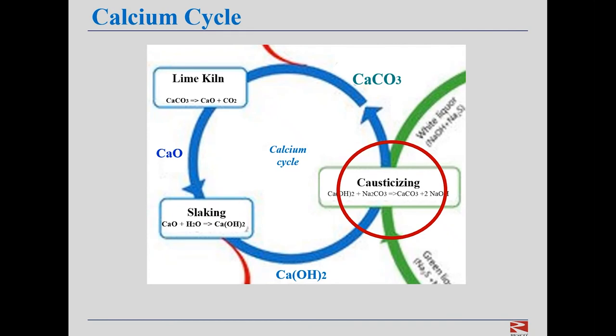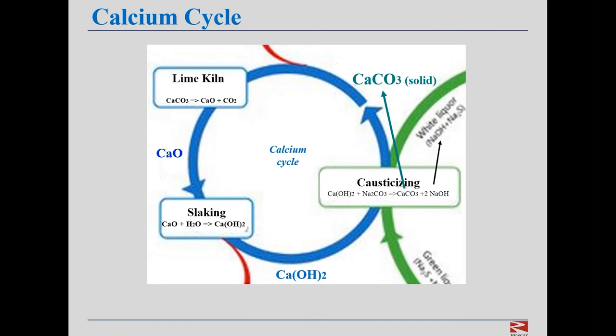The starting point for the calcium loop is the causticizing reaction. In the causticizing process, the calcium carbonate precipitates out of solution as a greenish-white mud, which is sent to a filter for washing, removal of residual soda, and dewatering. The feed to the lime recovery kiln is a slurry that typically contains 70% to 75% solids. The lime kiln then burns the calcium carbonate into calcium oxide or lime, and the lime is returned to the slaker, completing the loop. All in all, there are at least seven steps in the wood digestion and chemical recovery process, and each step has opportunities for upsets where any downstream equipment has to be throttled up or down.